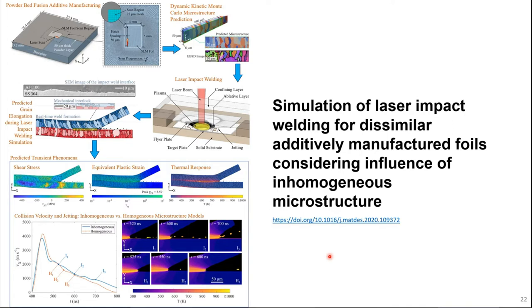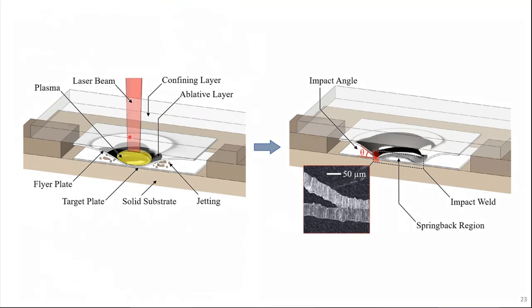And what I want to focus on is how we made the grains in an Eulerian system. Note the difference from the Lagrangian system that I showed you earlier. So to give you an overview of what laser impact welding is, this is just a simple schematic of the setup. Again, you have this confining layer, which in this case is our borosilicate glass. You've got one foil layer which is attached to it with two-way tape. The foil layer is also painted black. You have another foil layer which is attached to the solid substrate. And then you have your laser beam which comes and hits it from the top.